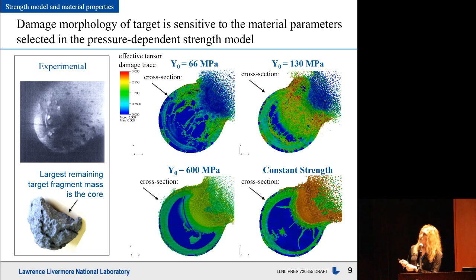When I increase it to 130, you can see this characteristic spall wall and a little bit of a preserved inner core, but not so much, and over time, eventually, the whole sphere fragments.